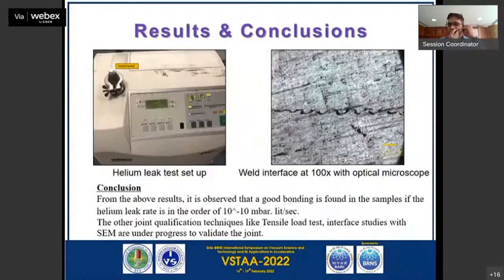Next slide, please. Sir, we have welded a few samples, and it was noticed that a good bonding is achieved when the helium leak test is in the range of 10 power minus 10 millibar liter per second. And this wavy pattern is a typical phenomenon which occurs in impact welding, like explosive welding. And this joint will be qualified for other tests, like a tensile test to check the mechanical strength. And we are using scanning electron microscope to check this.